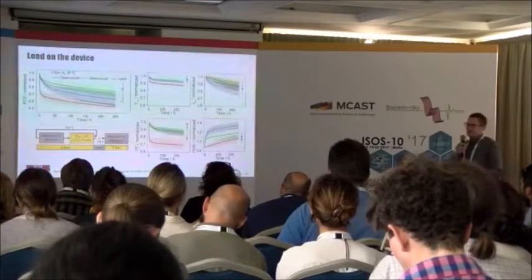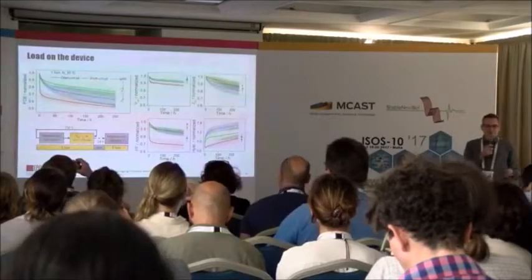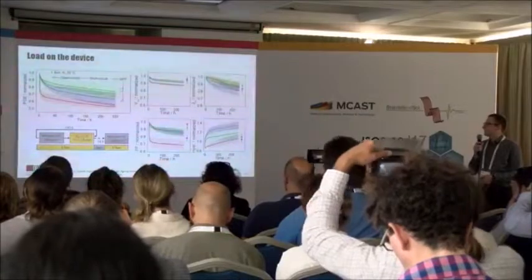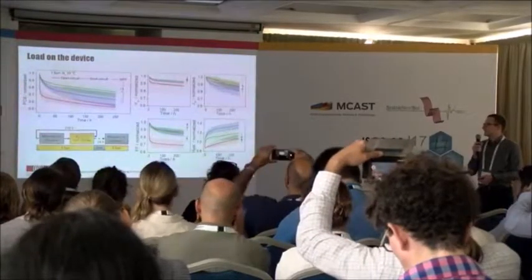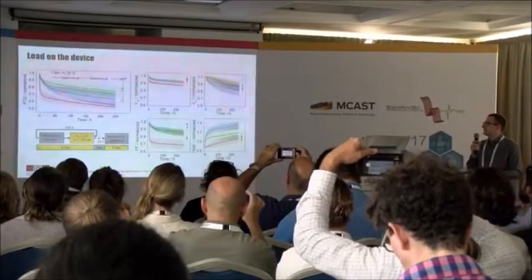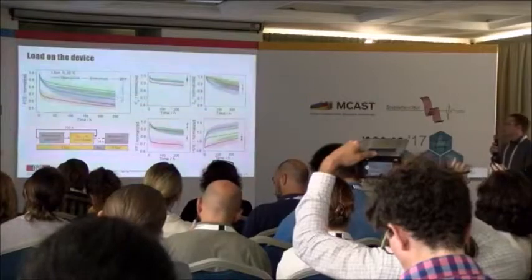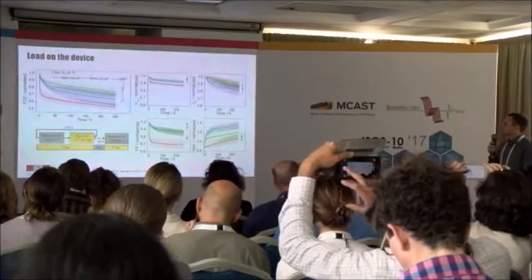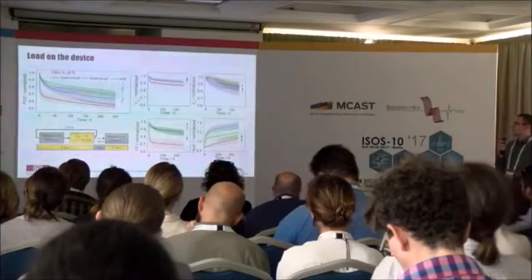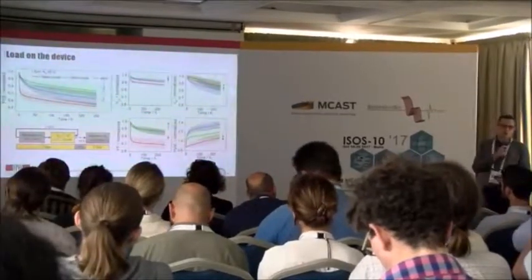And then coming to the load conditions of the device, this was discussed here quite a lot. We again measured many different devices under different load conditions. We find that the VOC kills the devices the fastest with the most limited recovery. JSC and MPP are more gentle for the devices, and they also recover to very similar values. At VOC, or open circuit conditions, we see that the fill factor and the loss of VOC contribute the most